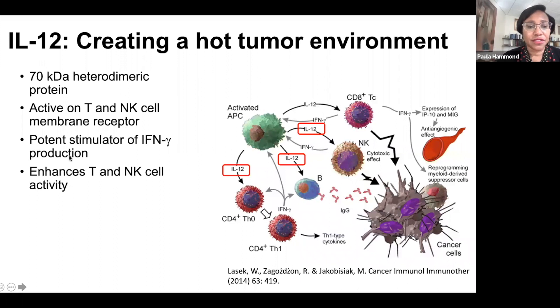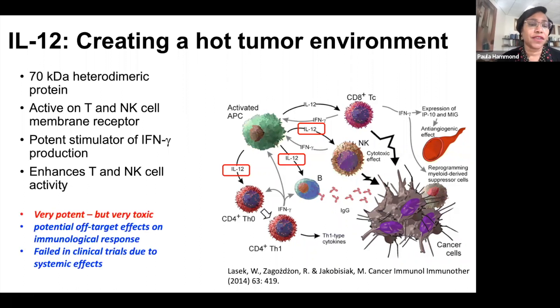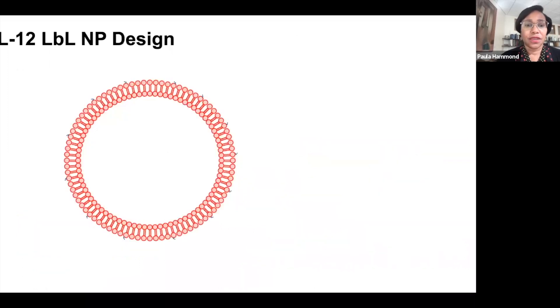The problem is that if IL-12 gets into the bloodstream, it's extremely potent — it can activate a systemic immune response that can be powerful and has failed in clinical trials due to systemic effects that can even cause death. So the idea is: can we deliver IL-12 directly to tumor cells without the safety issue? We use our high-affinity ovarian cancer cell formulation — the liposome again — and bind our IL-12 to the outside of the lipid layer using a nickel his-tag attachment, which gave us the highest loading. We then drape our polymer around the outside of the liposome, adding polyarginine as a positively charged layer, with polyglutamic acid as the outer layer of choice for sticking to the outsides of these cell membranes.